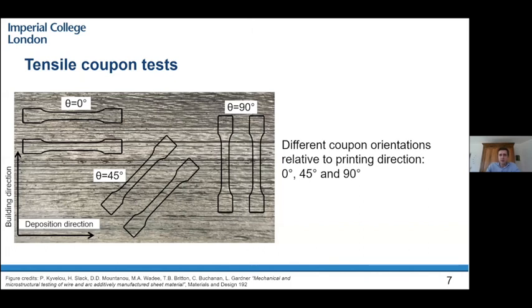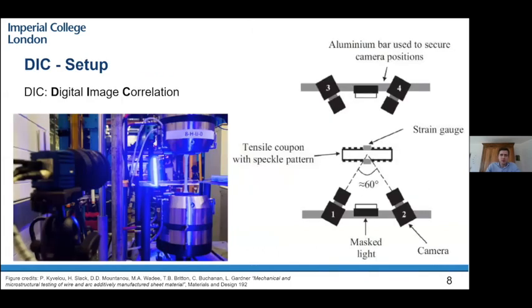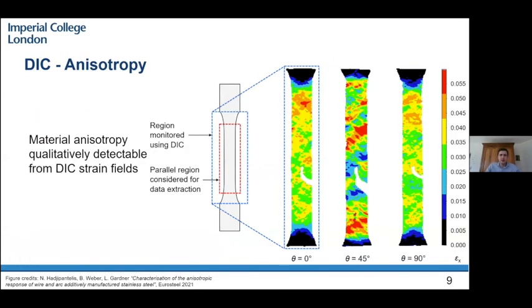Measurement of our tests was done using DIC, digital image correlation, with a 4-camera setup. Why a 4-camera setup? So we were able to measure both sides of the coupon, and also a stereoscopic image, which in the end led us to measure not only longitudinal and lateral strains, but also through thickness strains of the coupons.